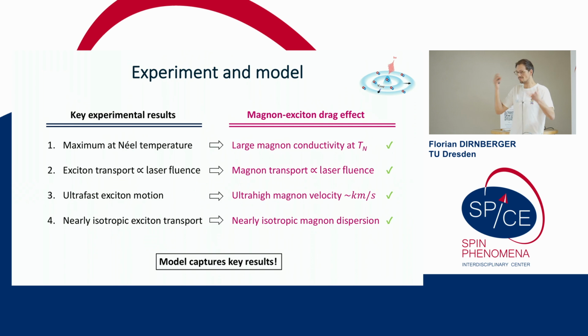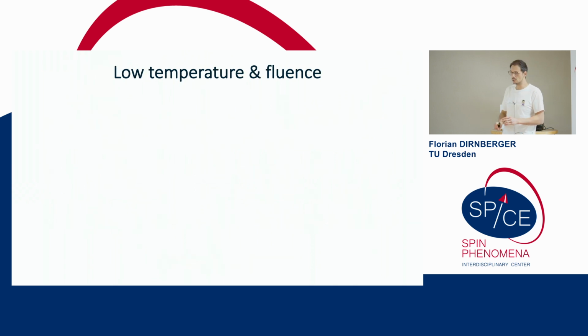So with this general idea of the magnon-exciton drag effect, we believe that we have found a reasonable framework to account for these very interesting experimental phenomena, in a semi-reasonable way, I would say. So this captures a lot of the phenomena that we see at intermediate and high excitation fluence and throughout a large temperature range.